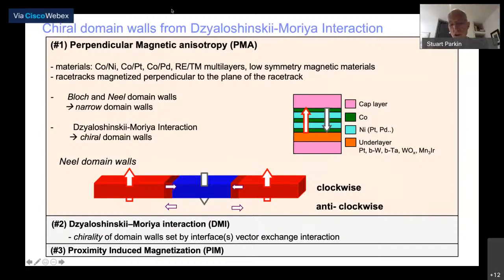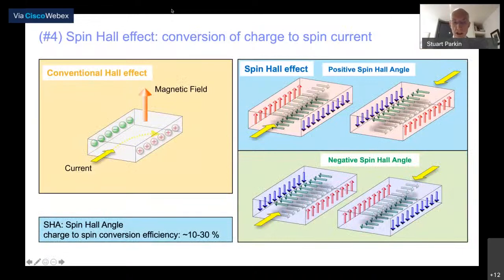Another important physics is the proximity-induced magnetization within these metal underlayers. I don't want to talk about that. Rather, I want to briefly mention another effect, which is key to racetrack, which is something called the spin-Hall effect. So you're all very familiar with the Hall effect. If you apply a current in a metal in a perpendicular magnetic field, then you will cause an imbalance in the electron density, the Hall effect. In the Hall effect, you see a voltage lateral to the current. Now, the spin-Hall effect is there is no voltage appearing laterally and no accumulation of electronic charge, but rather you get an accumulation of electron spin, as shown in the top right of this figure. On the left side, as you pass current shown in yellow into platinum, you see electron spins appear which are oriented in the red direction, and on the other side of the wire in the blue direction. And it turns out that this is a chiral phenomenon.